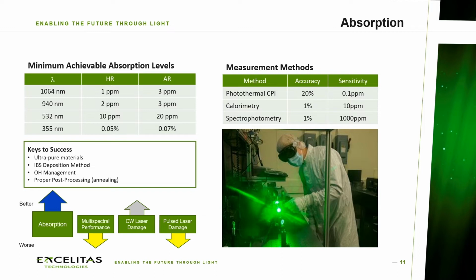And this is going to be at a level that really is typically not going to be problematic then for thermal effects within a laser. There may be localization of that absorption around defects that could be more problematic, but as a general rule, in the quality of the film, if you're in the neighborhood of a few ppm, typically speaking, that's not going to cause enough heating to be problematic. There are several different ways to measure absorption, and this is something that's often debated.